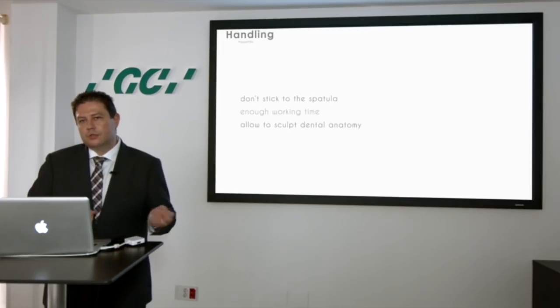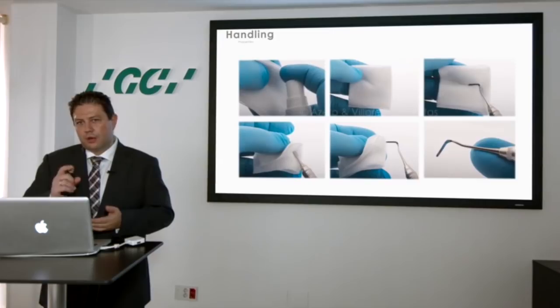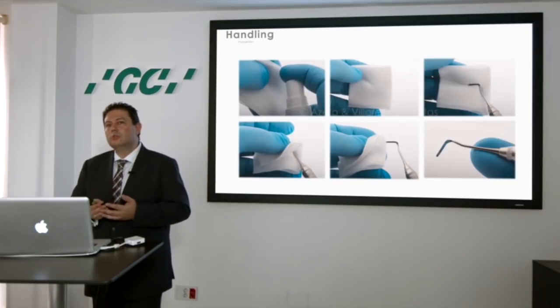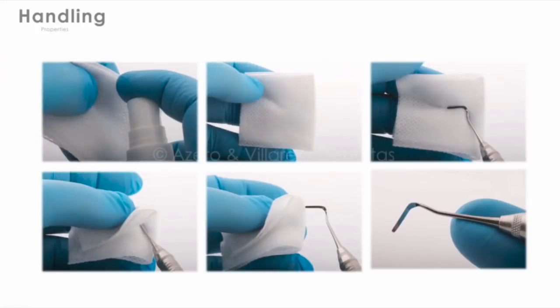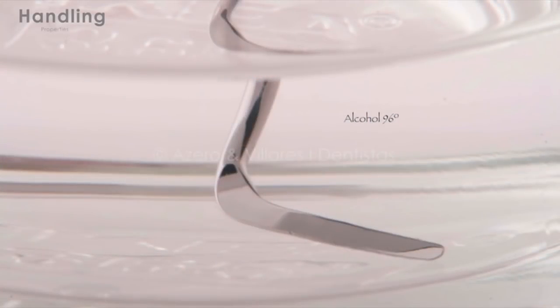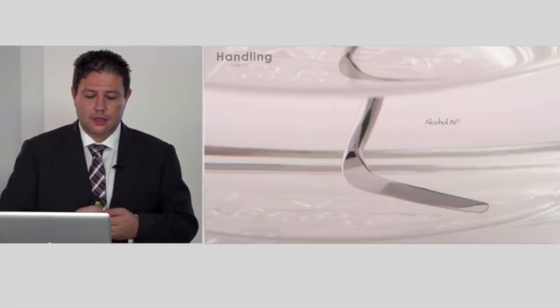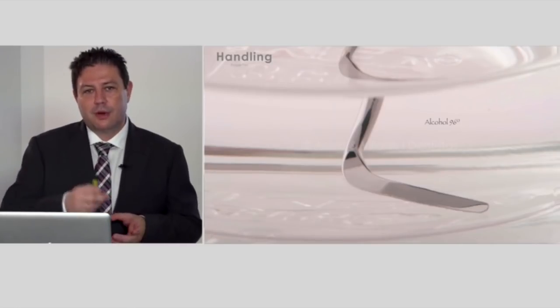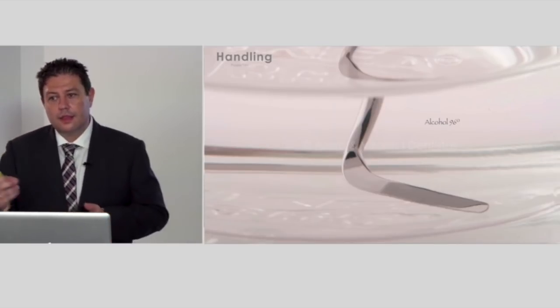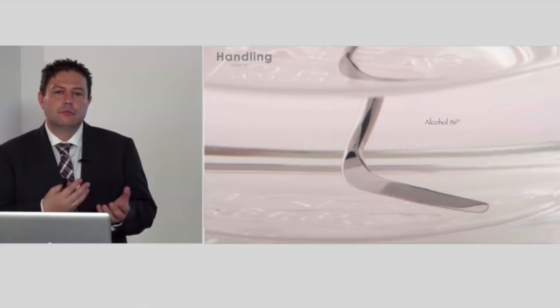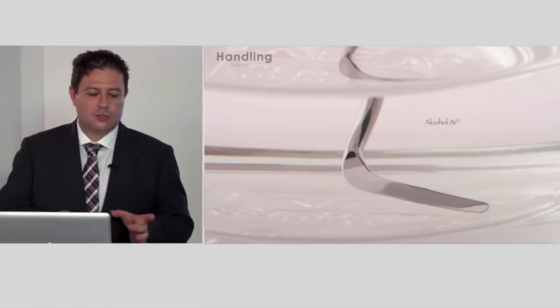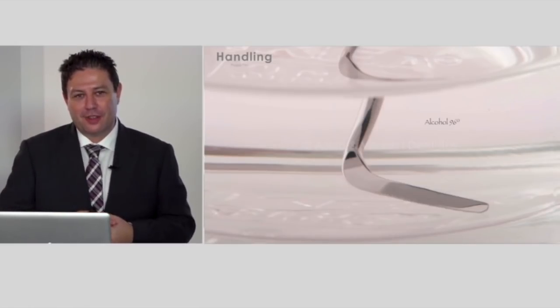There are some things that we can do to improve the handling of the materials. One is that we normally use some gauze on the spatula with a spray of alcohol, and what we do is to keep our spatulas dry. With the spatula dry, we avoid the spatula sticking to the composite or the composite sticking to the spatula. That is something that can make your treatment very horrible. There are other people who don't want small hairs of the gauze on the spatula, so they put the spatula into a glass of alcohol, and then they dry it in the air to have a very dry material. But for me it's not so good to have a glass of alcohol there working next to the patient.